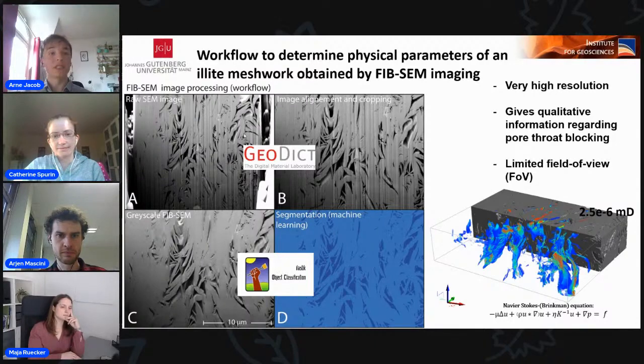As you can see in image C, the image segmentation with gray value intensity thresholding would not work for FIB-SEM images. We used the software ilastik to segment this by supervised machine learning segmentation. This built-in classification module groups the probability of each pixel to be assigned to a phase according to the different image features. So if you have a sharp border, that will be taken into account as well as the gray values.